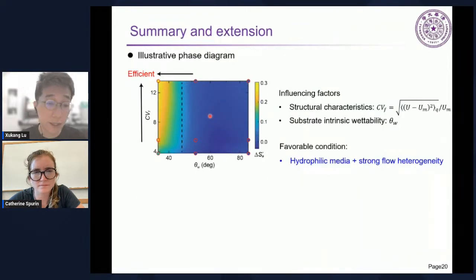So finally, we have this illustrative phase diagram. So to say when nanoparticles can be efficient for multiphase flow control, we have two influencing factors: the structure characteristics quantified by this coefficient of variation, and the substrate intrinsic wettability because of the corner flow criteria. So generally, a more hydrophilic media and stronger flow heterogeneity will benefit nanoparticles to play their roles.